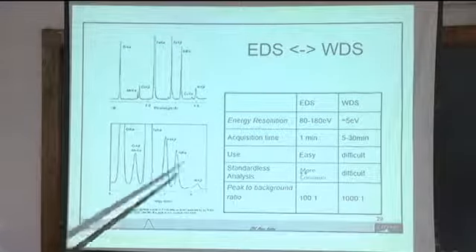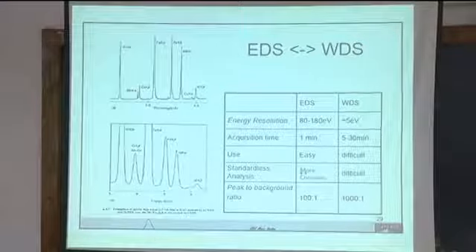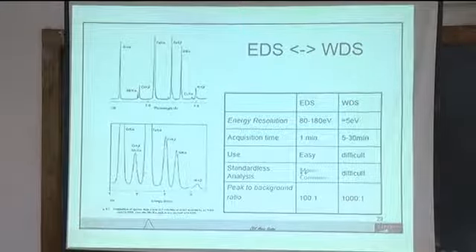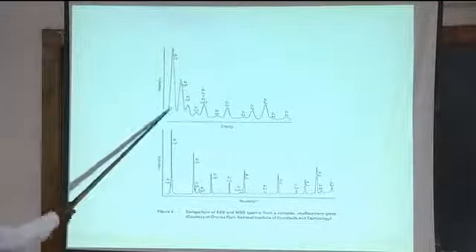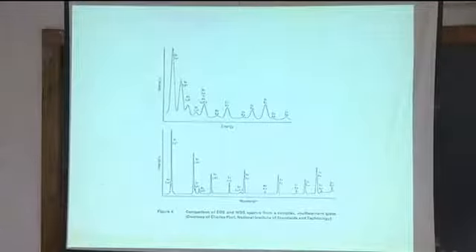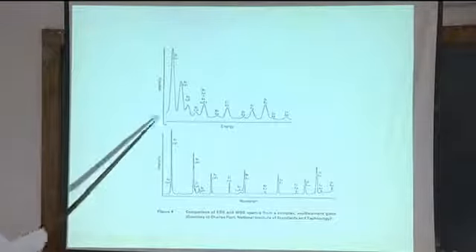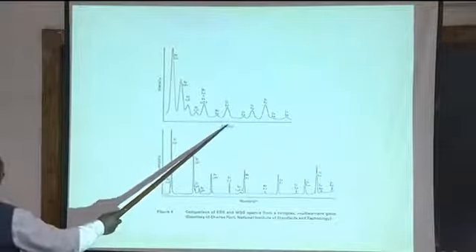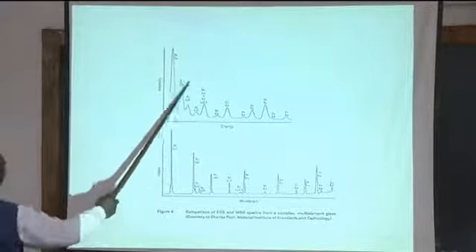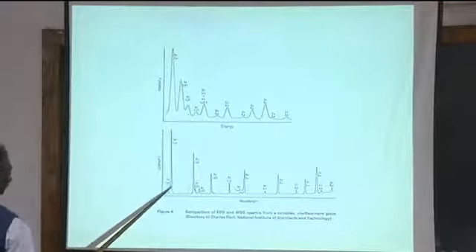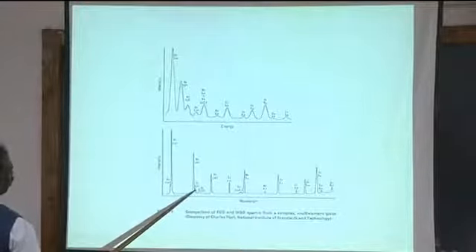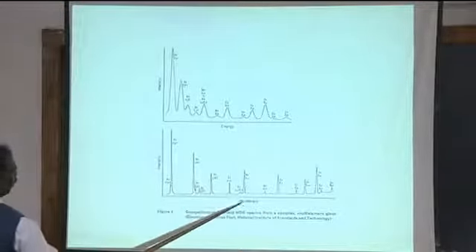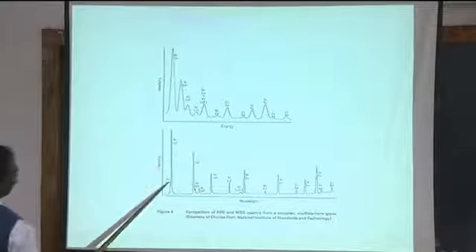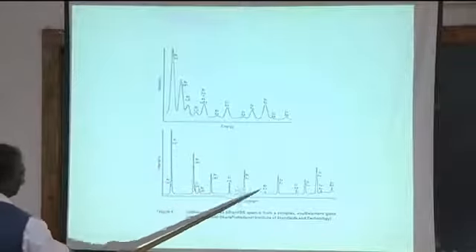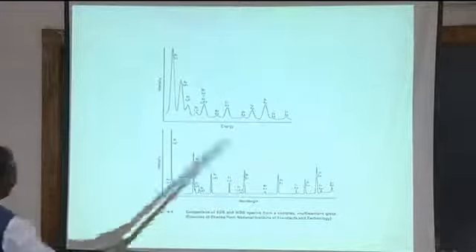This is a typical spectra for a WDS and EDS. A comparison for a particular scan is shown here. With EDS, because of the poor energy resolution, each peak is very, very broad, and if you have any narrow details, you lose them out. WDS, because it has better resolution, can reveal these peaks. That's the comparison.